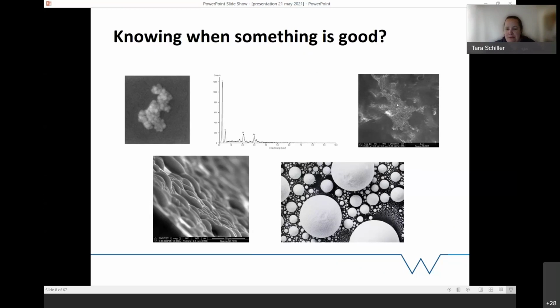With the top right, we can see that there's a pretty little pattern in the middle. What we had was an interpenetrating network, and with the interpenetrating network, we etched away one of the phases to see the silver particles that we generated in situ through a hexafluoroantimonate salt. The thing is, we don't really know if this is between the phases or in the phase that we etched away, but you know, it's still nice to get somewhere with things.